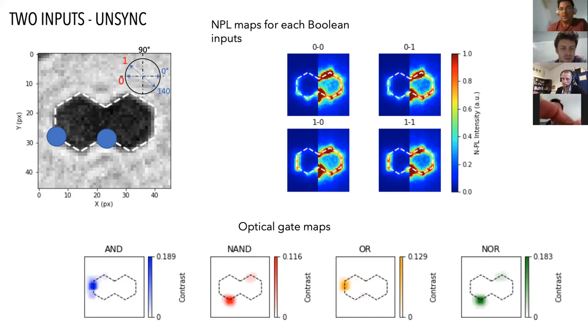But now I commented on this already, on this non-locality story, nice story that you showed. If I understood correctly, your explanation here is that the non-locality is mediated by the surface plasmon polaritons, right? That's correct. So I actually think that you don't really need the polaritons here. I would say that the energy, the heat, the temperature rise would also be mediated by just the electrons, by the thermal conductivity of the metal, which is extremely high.